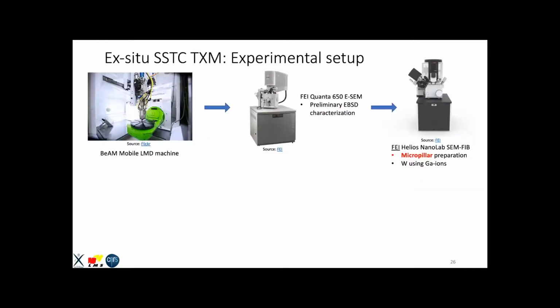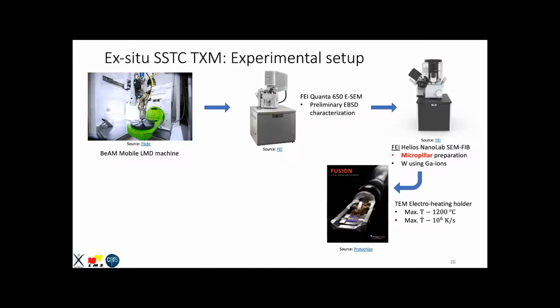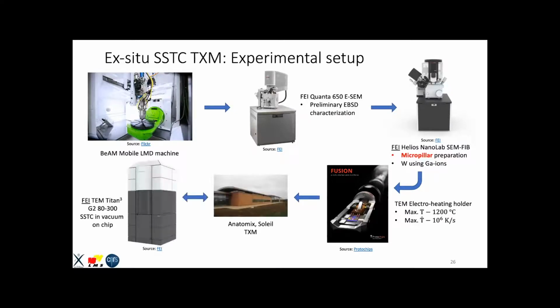Well, this is where we did what the French call bricolage. We made our micropillars with the FIB. Then we stuck them on this TEM electroheating holder. We went to Soleil, we did our TXM. Then we went to this TEM and we did heating and cooling on this. And we did a back and forth from Soleil to Saclay, even during night shifts, to do this experiment.